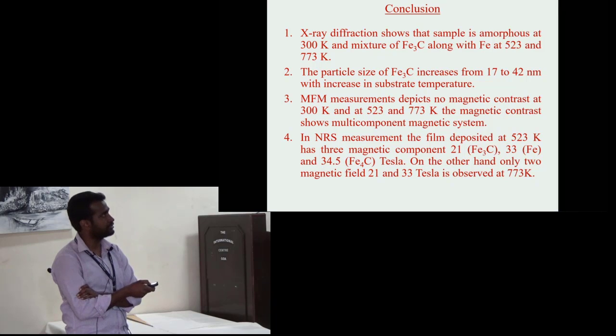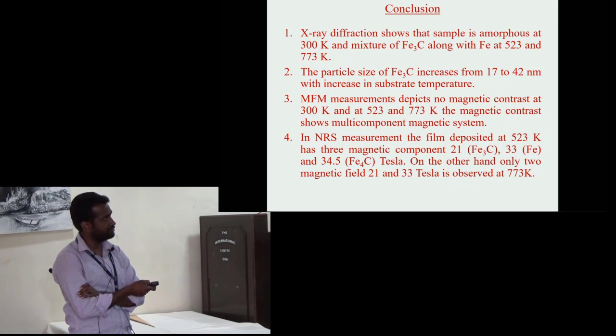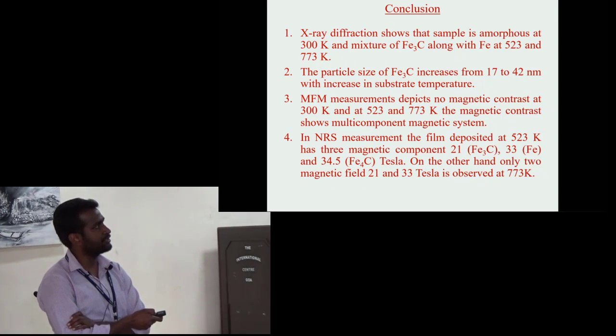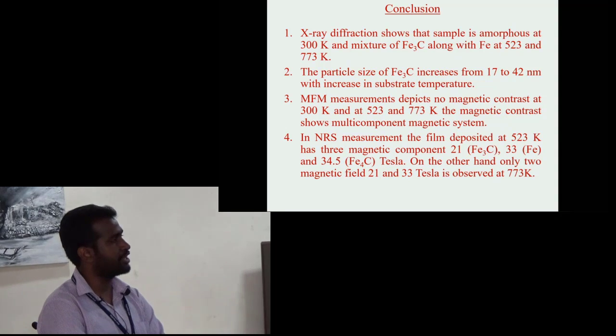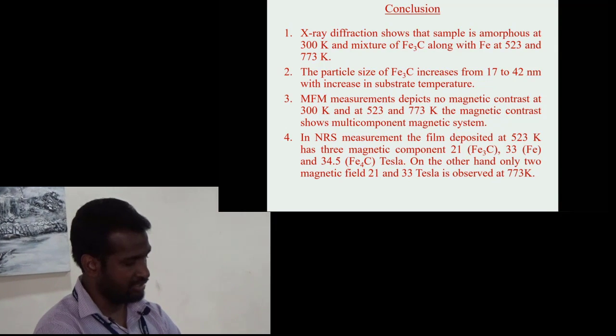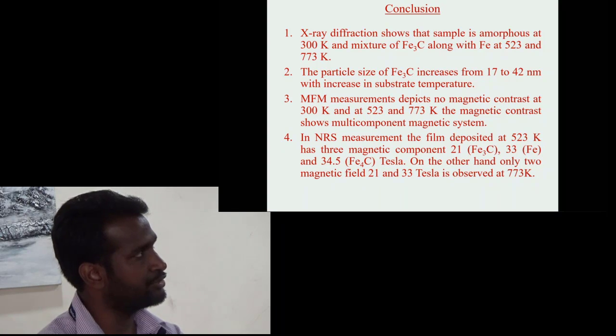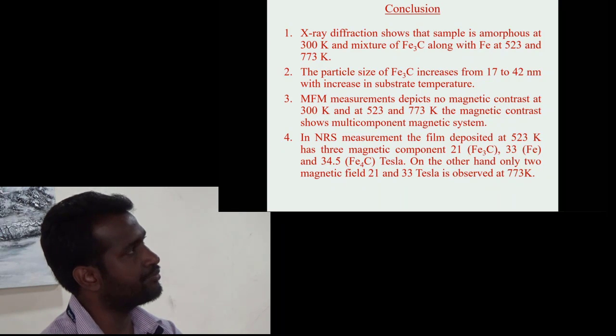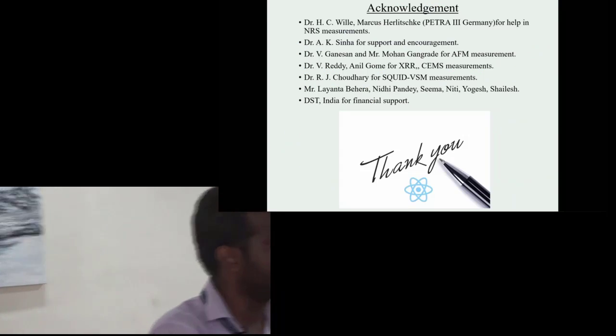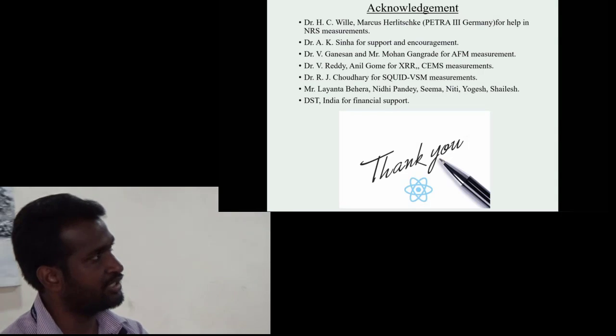And this is the conclusion. We have successfully investigated existence of Fe4C at 523 Kelvin, and it decomposes at higher temperature due to faster diffusion of iron-57. And this is acknowledgement and thank you.